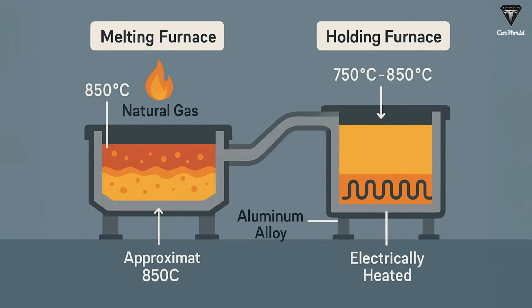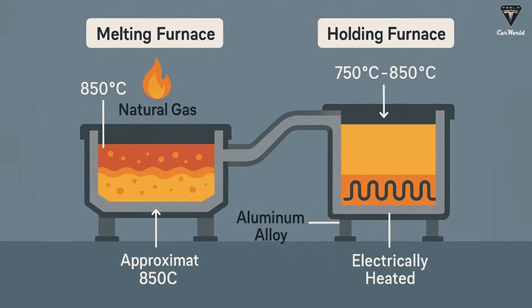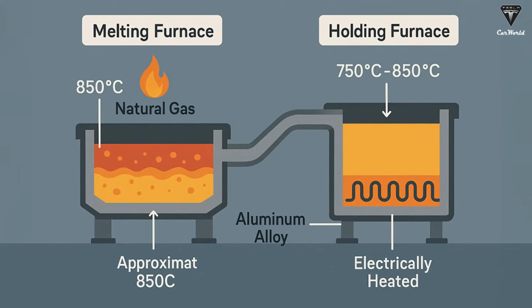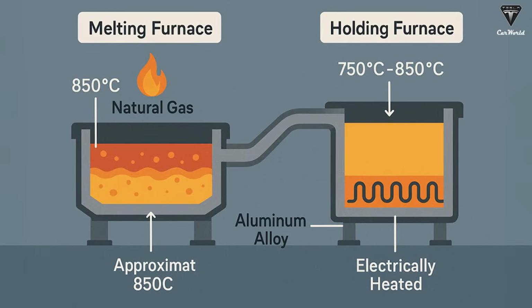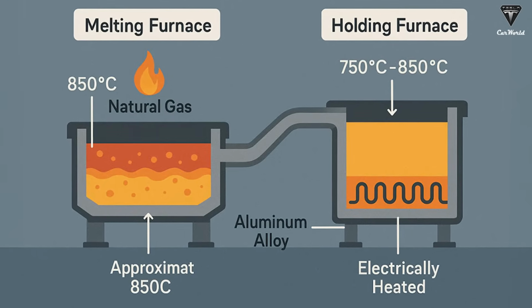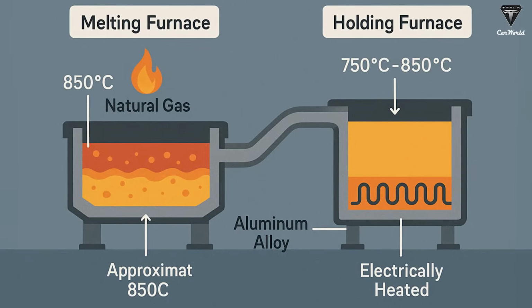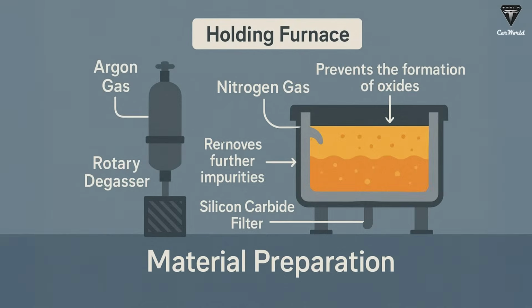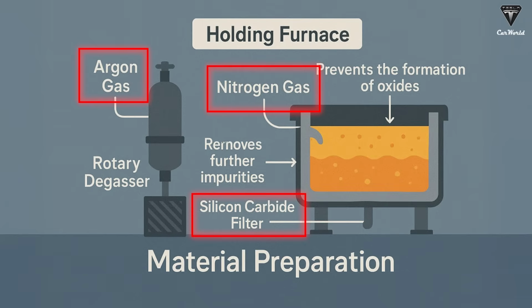The Giga Press uses a 2-furnace system to handle the aluminum alloy. One furnace melts the aluminum, powered by natural gas, while the second furnace, heated electrically, keeps the molten metal at a consistent temperature for casting, as mentioned above. The interior of the holding furnace is filled with nitrogen gas, which helps prevent oxidation in the molten aluminum and maintains a stable temperature. Additionally, argon gas, a rotary degassing machine, and a silicon carbide filter are used to remove impurities and particles larger than 25 microns, ensuring the metal's high quality.